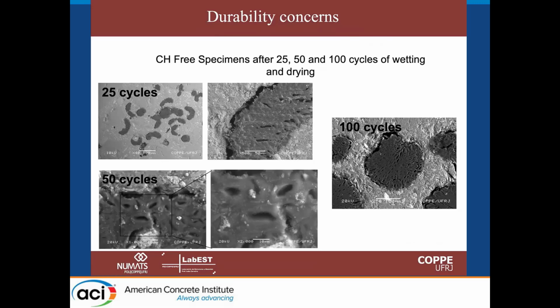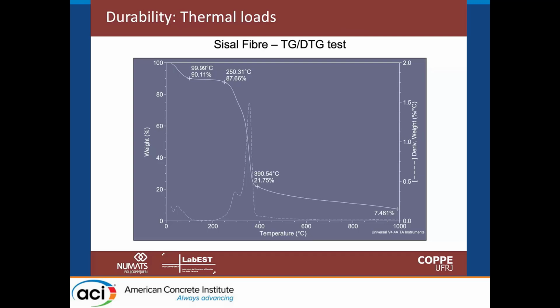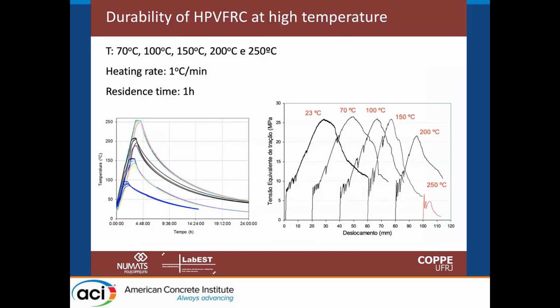Another important question is related to temperature stability. Normally, people ask how many degrees these natural materials can support. And we see here that up to 200 C, 250, up to this point, we do not lose much of the mass of the material. So it's quite stable up to this temperature. Then we have a strong decrease in mass because we start the degradation of the chemical components of the natural fibers. And when we test composites submitted to temperature up to 250 C, we see that up to 200, we keep very much this beautiful post-cracking behavior under bending.